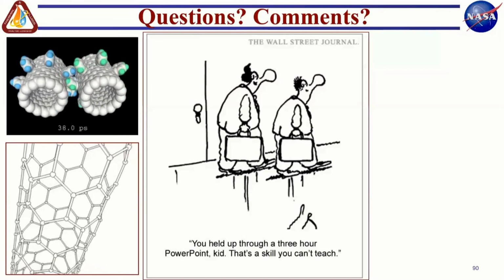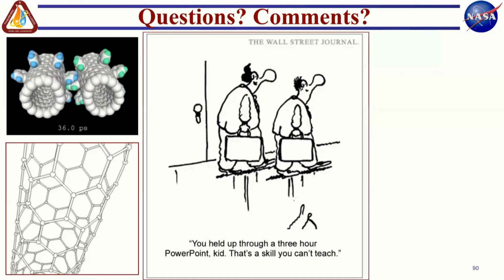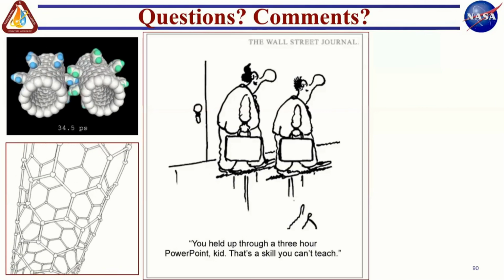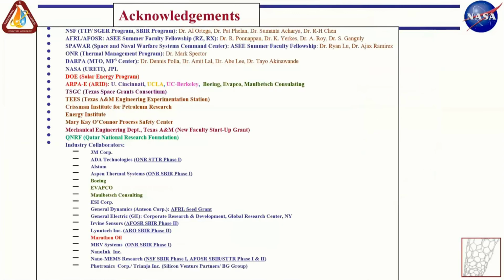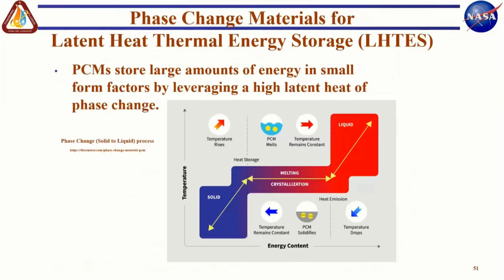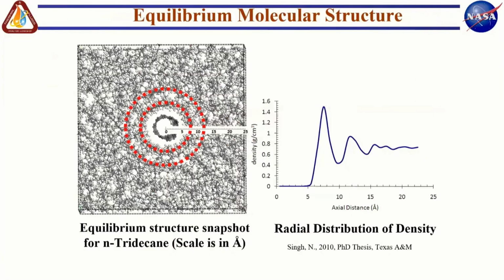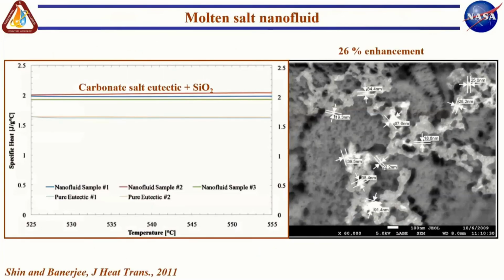And I have not even touched on the viscosity, because one of the things that happens is these nanoparticles tend to form a percolation network. I can probably show a quick picture to illustrate what I mean. And I didn't get time to talk about it. This also has big implications for magnetic nanoparticles, actually. So what you see in this picture here on the right is every time a nanoparticle forms, you form that ice layer, the compressed layer around it. But that's like the first order interaction. The second order interaction is two nanoparticles seem to know that they are close to each other because they form a tentacle and they join with each other. And you end up forming a percolation network. And that tentacle forms, I guess, because of the concentration gradient that you form between the two nanoparticles.